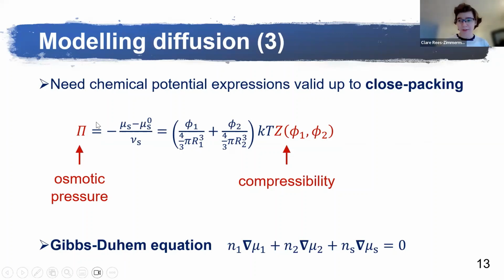It's because our film goes from dilute to concentrated to close packed over the course of drying. I did this by relating the osmotic pressure pi to the compressibility Z. The equation here is pretty much just the ideal gas law, pi equals NkT, modified by this compressibility Z. Mu S is the chemical potential of the solvent. Mu S naught is the solvent reference chemical potential. v S is the volume of one molecule of solvent. Then I relate the chemical potentials in the system together using the Gibbs-Duhem equation.